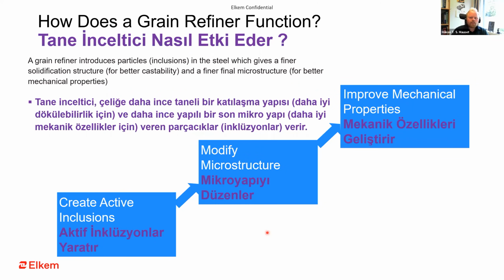So, but how does a grain refiner function? Well, what we believe, and you see a lot in the articles and theory, is that a grain refiner introduces particles or inclusions into the steel, which then should give a finer solidification structure, which also should give better castability, and should get a finer final microstructure for better mechanical properties. So essentially, you should create active inclusions in the molten steel. This will modify the microstructure, both during solidification and finally, and this should improve the mechanical properties.